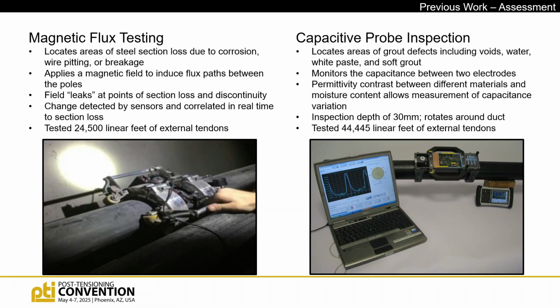Capacitive probe inspection also runs along the free length, but here we're looking at issues in our grout. So we're looking for grout issues like voids, water, white paste, soft grout. When you do find something, you can only see a little over an inch into the grout volume. But when you do get to a location of concern, you can rotate it around the duct to get a cross section of what's at that spot, and then take multiple slices with the device along that length and get a volume for that anomaly.